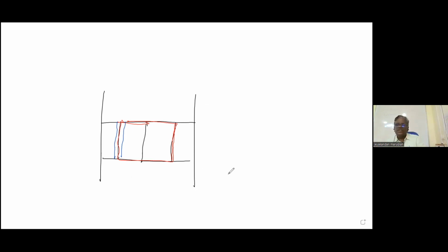Okay. Bottom welds, generally, what are the bottom welds? We are using a lap joint. This lap joint is welded only on one side. You can remove this weld by gas cutting or grinding, that is called deseaming, and lift the plate separate. Either you can deseam it, or if you want to cut the plate away from the weld, it should be minimum 2 inch away from the weld. Any lap welds, deseaming is allowed. Deseaming means grinding and removing the weld and lifting the plate. Lap weld, or 2 inch away from the lap weld.